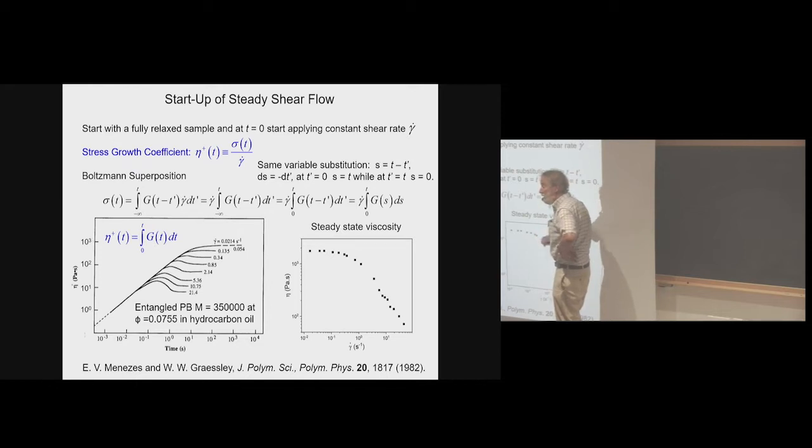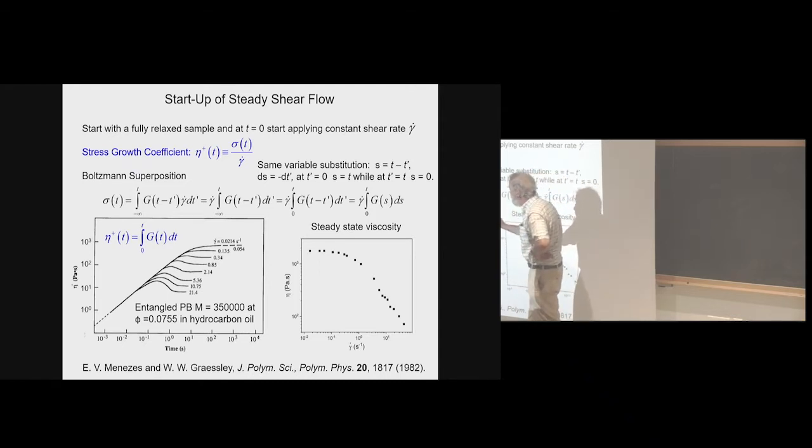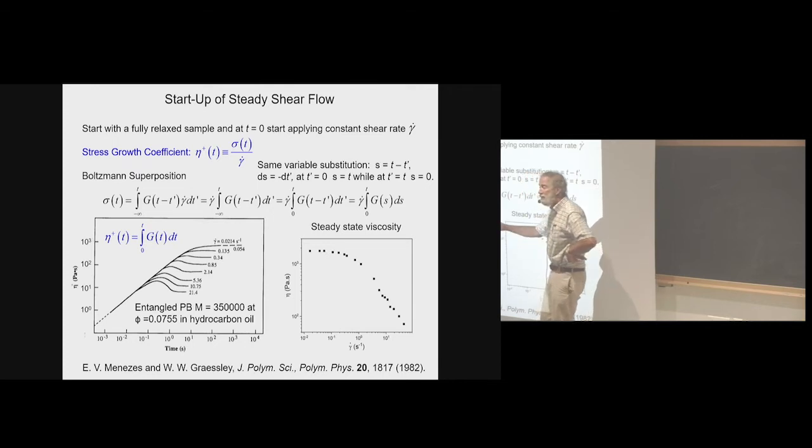data. So as the editor of the Journal of Rheology for the past 10 years, I can tell you there's lots of people that want to publish these data, and I say, no, I want to see these data first, because the default of the rheometer is I'm going to shear for 10 seconds, and then I'm going to signal average for 10 seconds. So I ignore the first 10 seconds, which is hopefully all this wiggle, the rise and the fall and all that.